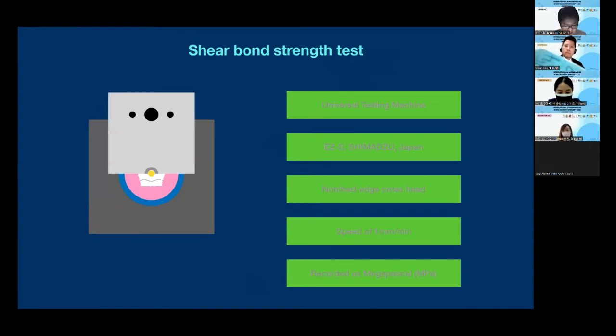Then the samples were tested with the universal testing machine from Shimadzu, Japan. The notch of the crosshead was aligned directly over the composite rod and flush against the tooth surface. The speed of the crosshead was set at 1 millimeter per minute until the bond failed, and the result was recorded in megapascal.